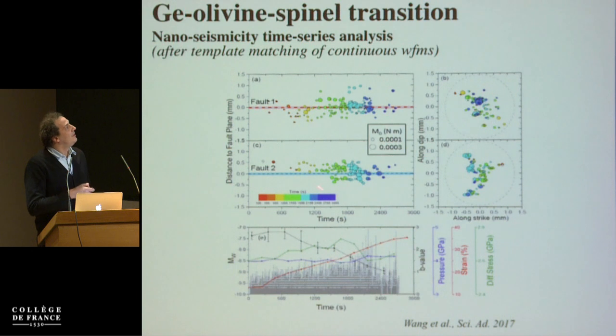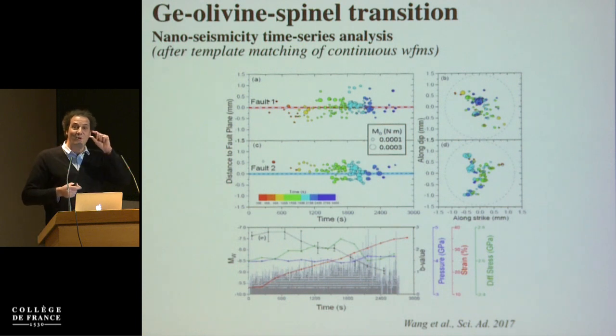And if you do so, this is the time as a function of distance. So you see the events on fault 1 and fault 2. You maybe see some migration here, actually. But I think what you see clearly is that at the beginning you have small events and you tend to get larger events later on. And if you look at the evolution of the b-value during the experiment, this is the black line here, you see that at the peak of seismicity, so basically when the sample breaks, we do have a minimum in b-value and a peak of seismicity. So it's telling you that this small olivine sample prepared its failure at high pressure. So you do have a nucleation phase. Obviously you have to have a nucleation phase, but here it's very clearly shown.